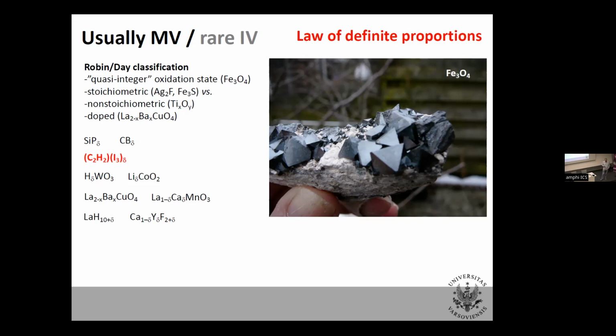So is Fe3S. You probably never heard about this compound because it does not exist on planet Earth at normal PT conditions. But it exists at high PT conditions, and it is an immensely important compound. Because all theories about how the nucleus of Earth looks like, and that's made of iron and nickel, of very heavy elements, have recently been shaken by those discoveries that some sulfur, a light element, can actually dissolve into the core and can form compounds like this. So there is some cycling of sulfur even in the deep core of planet Earth. And this, again, is a peculiar compound which has just one type of iron in its structure. And it's not iron 1 plus or 0, that's intermediate valence.